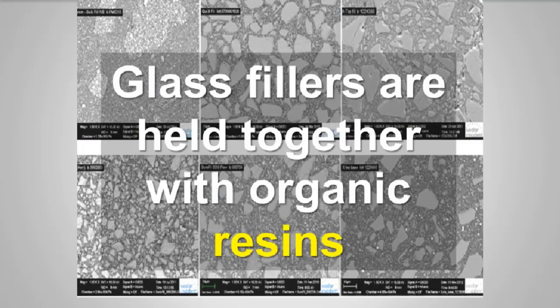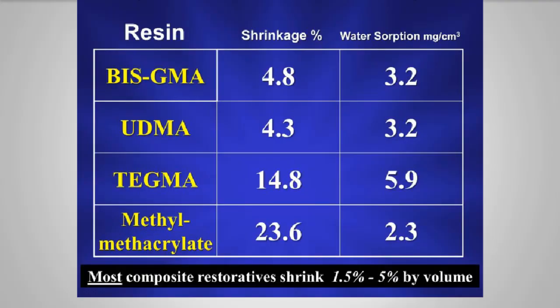with resins. And virtually all composites in the marketplace today still employ either bis-GMA, synthesized by Ray Bowen way back in 1962, or urethane dimethacrylate as their primary resins, or sometimes slight variations of these. And these are typically thinned out with lower molecular weight resins such as TEGDMA, triethylene glycol dimethacrylate, that is, or other proprietary resins that thin these out a little bit. Methyl methacrylate, which is not used in composite manufacture, is shown here just as a basis of comparison.